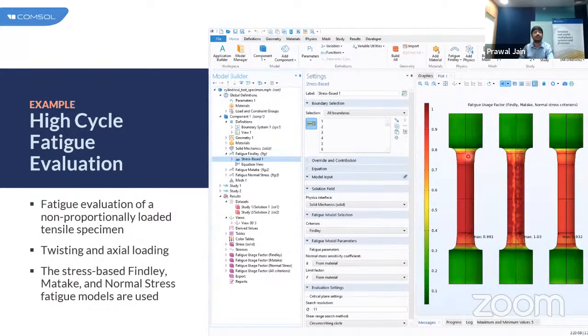And again, we have an interesting example from high cycle fatigue, which is about a non-proportionally loaded circular test specimen, which is also a benchmark model. Here we compared three different methods, which are Findley, Matake, as well as normal stress. But in this case with Matake, since these methods are based on critical plane, we can see that the stress distribution or the fatigue life is not very smooth, which means that the critical plane selection we made during the problem setup certainly needs a change in selecting the correct shear planes.